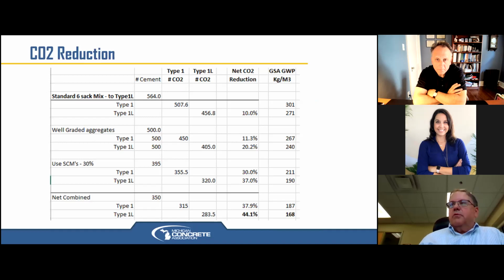Now, what does that really mean? This is basically answering Arnold. If we took a standard 6-sack mix with type 1 cement, we're going to be right around 301 on the global warming potential. If we just switched to a type 1L cement, we would reduce that amount by 10%. So that's a straight 10% reduction.